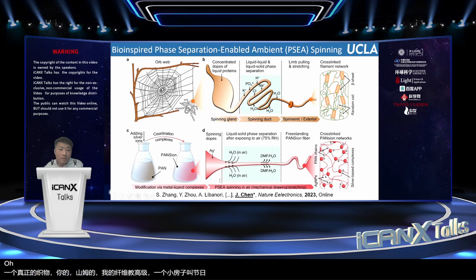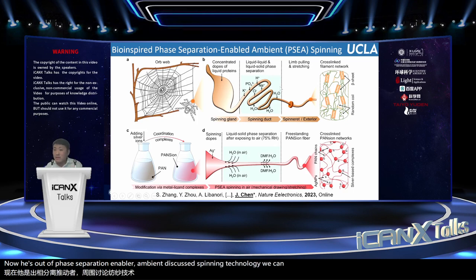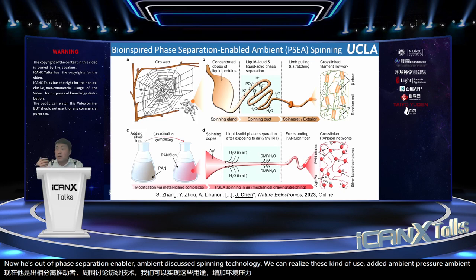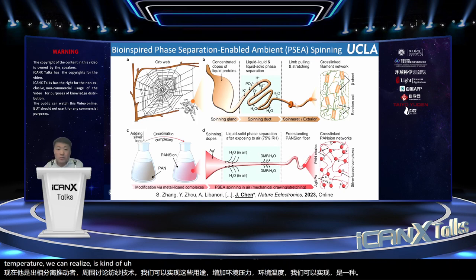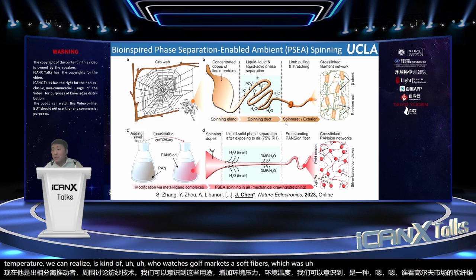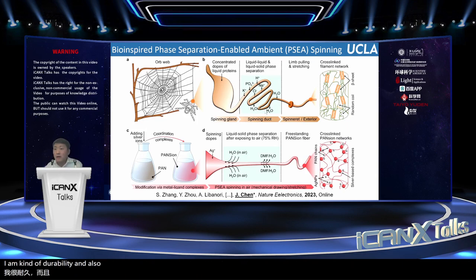Recently we published a paper in Nature Electronics. We used a phase-separation-enabled ambient dry spinning technology, which can be carried out at ambient pressure and ambient temperature. We can realize large-scale fabrication of soft fibers which have high mechanical durability and are also electrically conductive. This can largely contribute to building smart healthcare textiles.